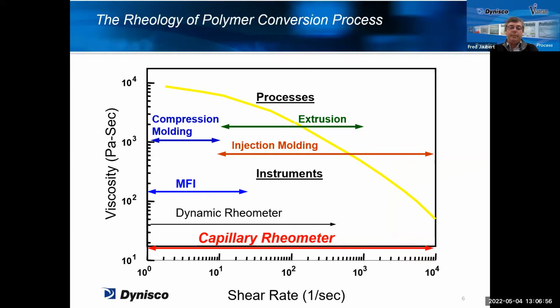So what is the advantage of the use of a different type of instruments based on your process of conversion? So if you are doing compression molding, for example, which is really a simple process, I would say, in sense of polymer viscosity, you can use a melt flow indexer. It's well used for this type of process. If you are doing extrusion, the melt flow index is still a valid measurement, but you are really at the border of the measurement with a melt flow indexer. And if you are doing injection molding, you have forces, so shear rates, which are much, much higher than in extrusion. And in this case, the melt flow indexer is absolutely not adapted. And this is where the capillary rheometer is really coming into play.